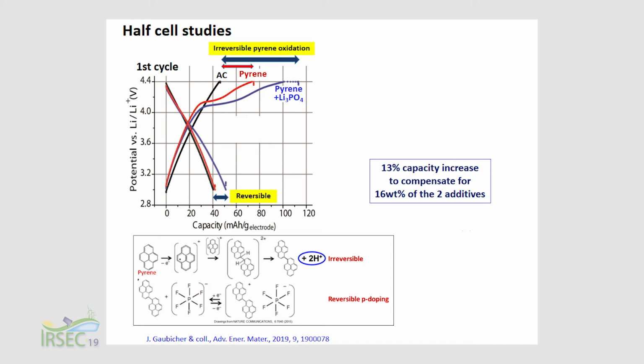So you can see in half-cell studies versus lithium metal that during the first charge in the electrode with only pyrene, we have extra irreversible capacity. This is what we expect. But during the subsequent discharge and subsequent cycles, we do not have more capacity. On the contrary, when we use both pyrene and lithium phosphate in the activated carbon electrode composition, we have more irreversible capacity, more electrons. This is what we want. That's a good result. And in addition, we have larger reversible capacity at further cycles. So this is coming from the second reaction, which provides reversible electrons. And this second reaction provides 13% capacity increase, which compensates for the 16 weight% of additives that we put as dead mass in the electrode.